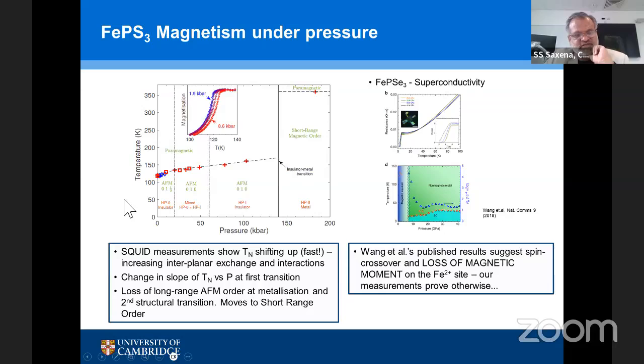So if you were to lay out the magnetic and structural phase diagram, you get this picture, which is, you see antiferromagnetism giving way to those structural transitions I mentioned. Eventually, it metallizes, and then you get short-range magnetic order. So you can see an insulator, a structural mix to again a new kind of insulator, and eventually a crash into a magnetic metal.